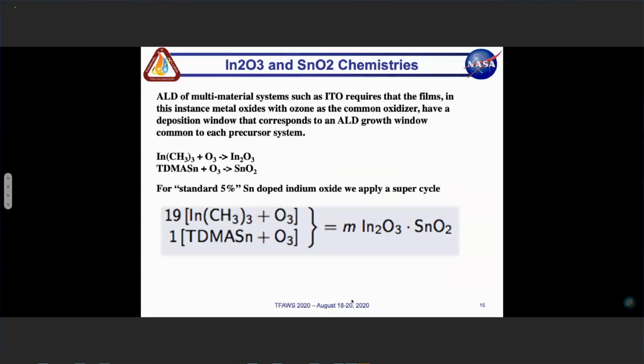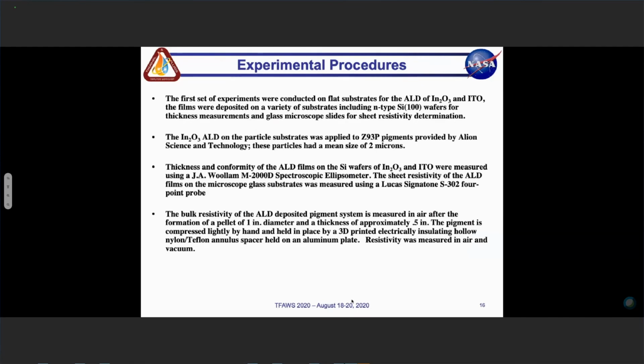So moving on, the materials that we actually use, what are called precursors for our work, for indium oxide or tin oxide, are trimethyl indium and ozone, and the other one is tetrakis dimethylamino tin and ozone. What we wanted to do is dope about 5% of tin within our indium oxide mixture. And the way we're able to do this is what's known as a super cycle. We went through an ALD process of indium oxide and ozone for X number of cycles, then we would throw in a single cycle of tin and ozone. Going through the cyclical super cycle process, we ended up with a very specific percentage of tin doped indium oxide that we can apply to our pigments themselves.